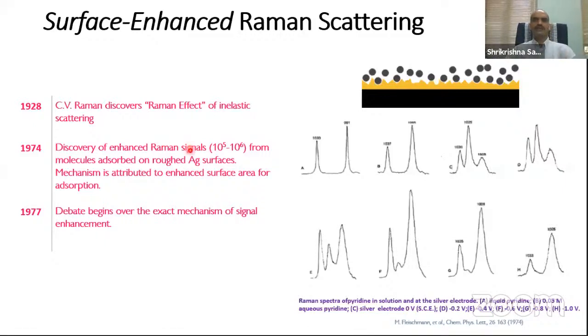It was an accidental discovery in 1974. One group wanted to study the Raman scattering of pyridine on silver. And they did some electrochemical treatment to the silver surface, and because of the electrochemical treatment, the silver surface was getting rough. What they saw was that if there is no treatment of the silver surface, they couldn't get any peak for the pyridine Raman peak I am supposed to see at this particular position.